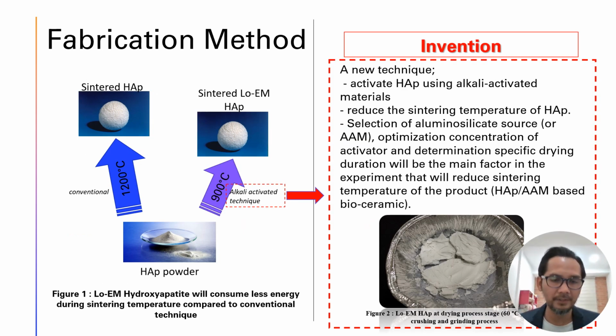Okay, so this slide basically compares the fabrication method of the conventional and Lo-EM hydroxyapatite. For the conventional, we sinter at above 1200 degrees Celsius, but for Lo-EM HAP, the trade secret is that we activate the hydroxyapatite prior to sintering, using the same conventional furnace but at a much lower sintering temperature, which is 900 degrees Celsius. Okay, so this is the invention.